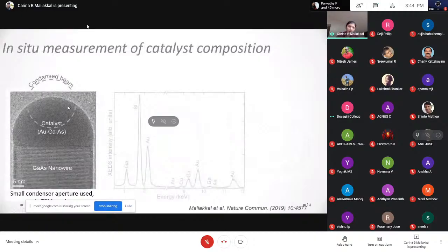So here the first example is where we are trying to measure the catalyst composition while a nanowire is growing. So what I have is a gallium arsenide nanowire. There's a gold particle based catalyst. So you started with a gold nanoparticle, which is a solid when we started, and then we increased to a reasonably high temperature and we introduced the gallium precursor and the arsenic precursor. What happens is that some of them mix with the gold and then it becomes a liquid.